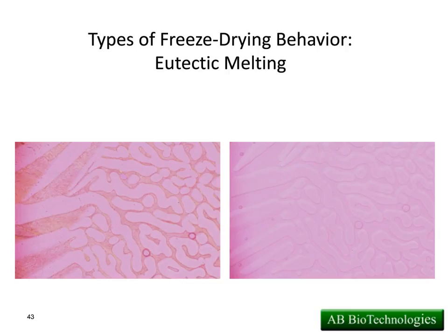Now, if we warm up, which is the image on the right, above the eutectic melting temperature, that interstitial space fluidizes. We've exceeded the eutectic melting temperature, but notice we have not exceeded the ice melt. So there's still ice in the ice channel, so this thing would still have solid structure, but if we tried to freeze-dry the one on the right, we'd just get a total eutectic melt, a puddle of goo in the bottom of the vial.